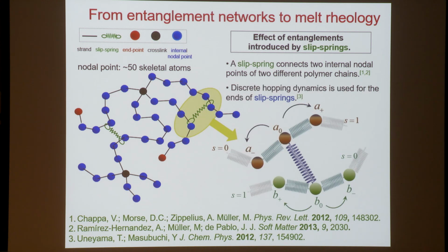This slipping motion is represented in our case as a sequence of jumps of the slip spring ends between successive segments of their chains. And we need rate constants to describe this jumping process. If a slip spring end reaches a chain end, then the slip spring may choose to slip off the chain, and so the entanglement is destroyed. However, new entanglements are created every time by chain ends as they seek to engage with surrounding chains. So there is a dynamical equilibrium. Technically, this is a grand canonical simulation with respect to the slip springs and canonical with respect to the chains.